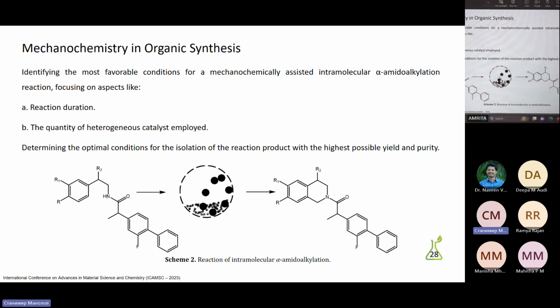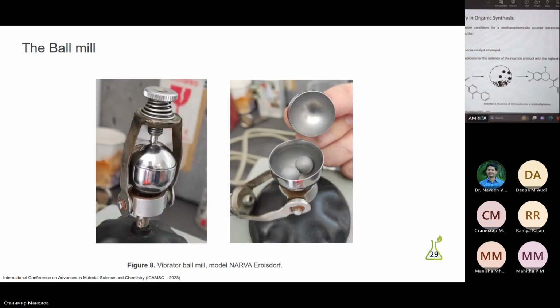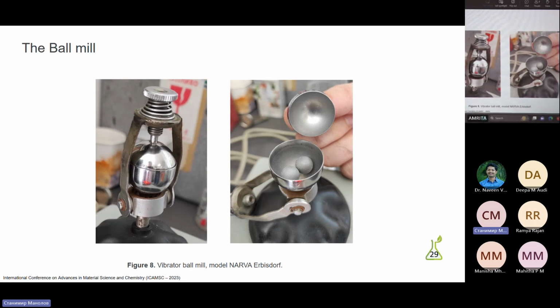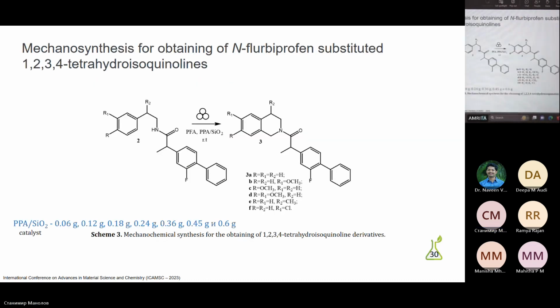This initial unsuccessful endeavor to perform the reaction in a mortar and pestle prompted a shift to employing a ball mill. So mechanosynthesis was conducted in our group using a ball mill vibrator, working with a working chamber of 4 milliliters, and the synthesis utilized two metal balls, each measuring 10 millimeters in diameter and weighing 4 grams. In the quest for optimization, we initiated the process by varying the quantity of the polyphosphoric acid on silica catalyst. All reactants, starting amide 2, previously obtained from our group, paraformaldehyde, and this catalyst, polyphosphoric acid on silica, were combined within the ball mill container.